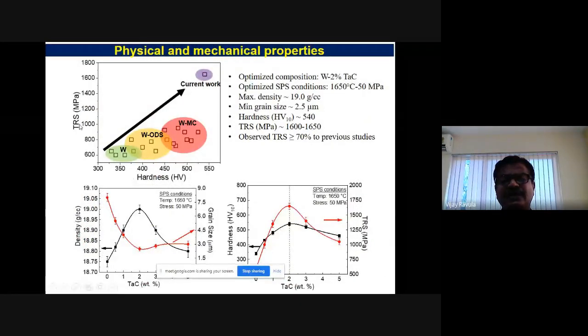So if you look at the transverse rupture strength versus the hardness, typically tungsten is here, ODS oxide dispersion tungsten is here, and metal carbide dispersed tungsten is here. But our work is right now over here, so it has got a huge strength as well as hardness. And these are all the conditions we have used.